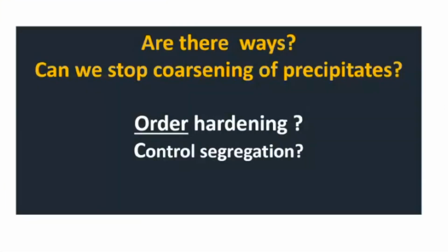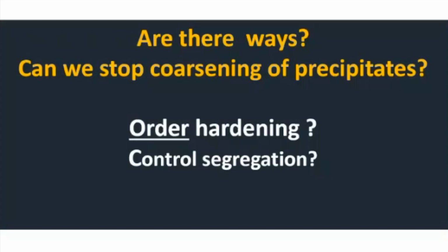How can I get a high temperature aluminum alloy which works at a reasonably high temperature in the context of the 600 degrees centigrade melting point of aluminum? There is a series of papers by Seidman where he used scandium ordered phase, hoping that the L12 phase probably can replicate the superalloys' gamma prime. Although it did not happen, that started the thought process.